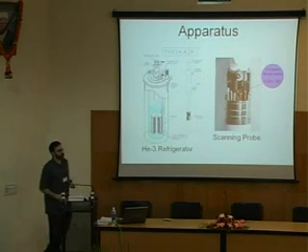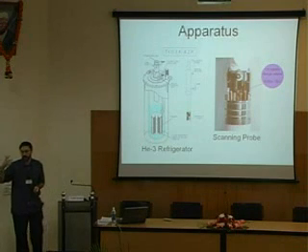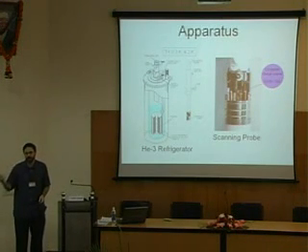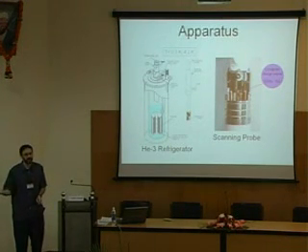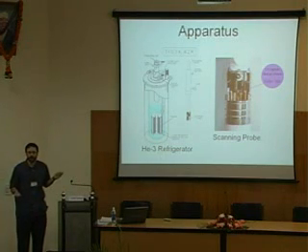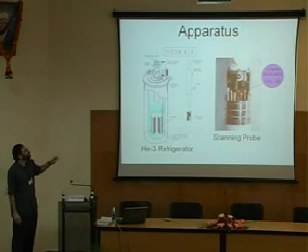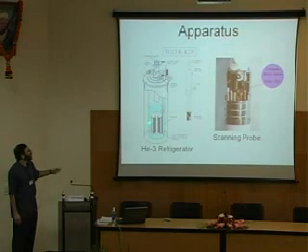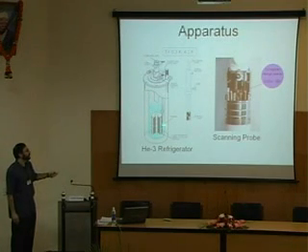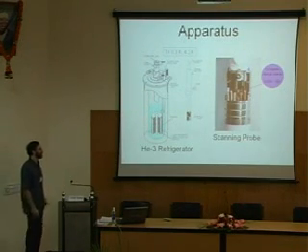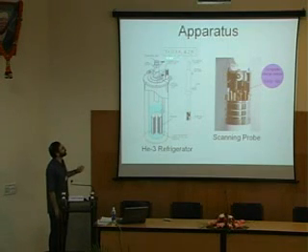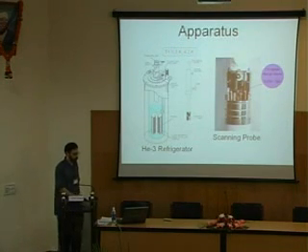This needs to be a low-temperature experiment. It turns out, as I've already mentioned, the quantum level spacing is set by the effective Rydberg. That's only 5 millivolts. This experiment won't work at room temperature. You need to be cold. So our apparatus is a helium-3 refrigerator. The microscope's on the end of a long stick, goes into the apparatus. The tip and sample end up directly immersed in helium-3, and we get this low temperature. For the data I'll show you, some of it was taken at 0.3 Kelvin and some of it at 4.2 Kelvin.